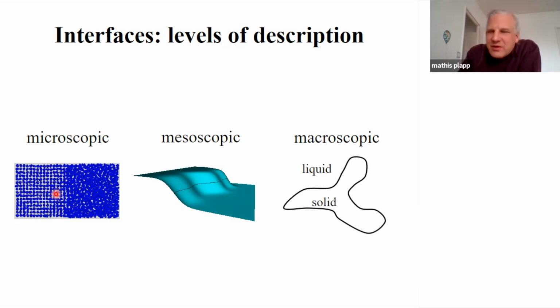And if we want to stick to a continuum description, but resolve the finite thickness of the interfaces, this is the mesoscopic scale. This is the scale where the phase field model lives. So here we have a function that can be seen as an order parameter that indicates whether we are in the solid or in the liquid. And the solid and the liquid correspond to two constant values of this order parameter. And the interface zone is a smooth transition between these two values.